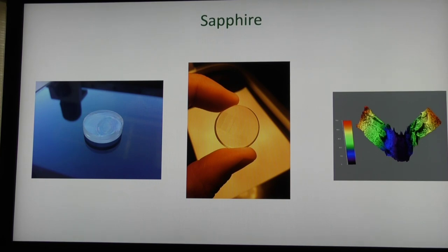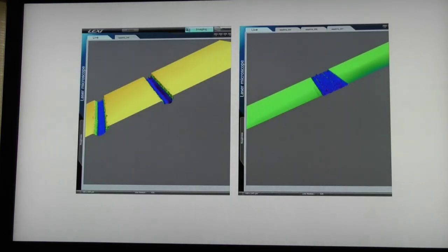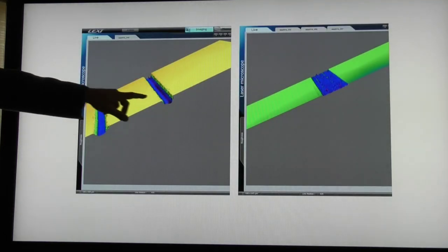Now, when I started developing the microfluidics lab, I started trying to push the envelope a little bit. The first thing I thought was to use sapphire, and that is because it's got excellent mechanical properties, very strong. It is chemically very, very resistant, very stable, and it's optically very desirable for imaging type exercises. So what we did, we took sapphire, and in collaboration with a colleague at the University of Wyoming, Dr. John Oki, and through him with Dr. Jeff Squire at the Colorado School of Mines down in Colorado, we used their femtosecond laser pulse systems to etch channels inside sapphire.